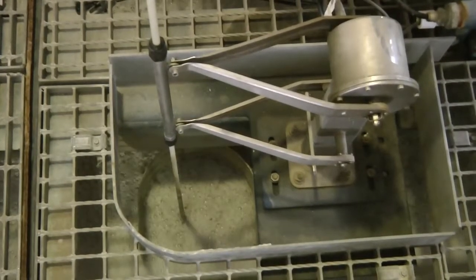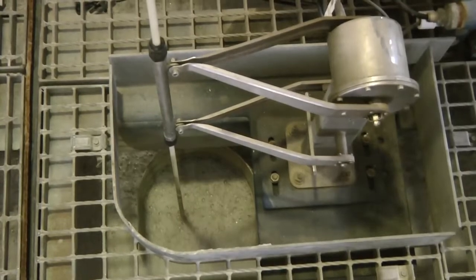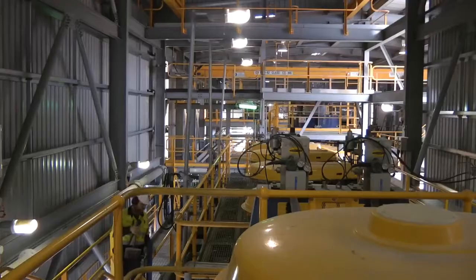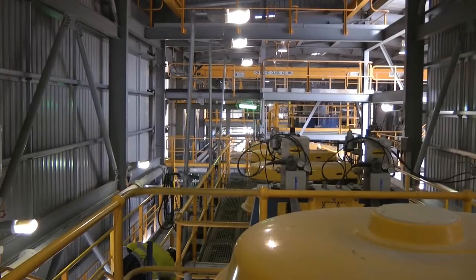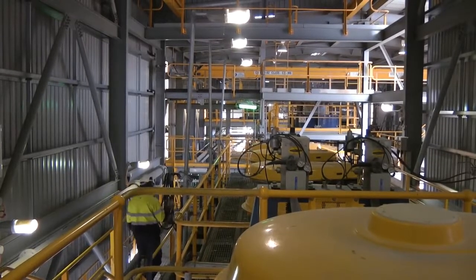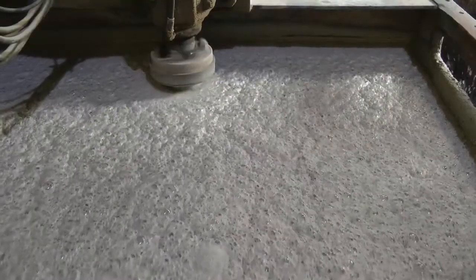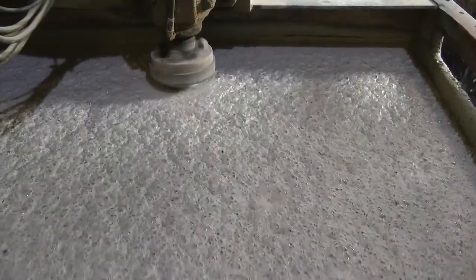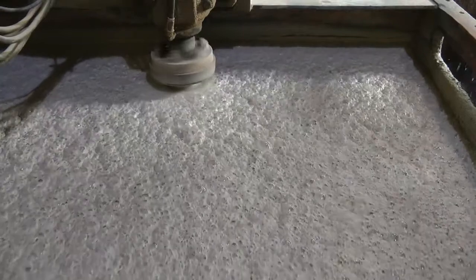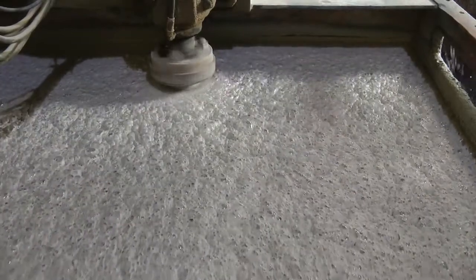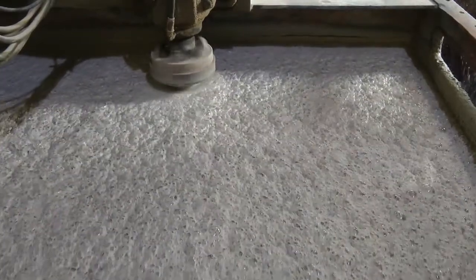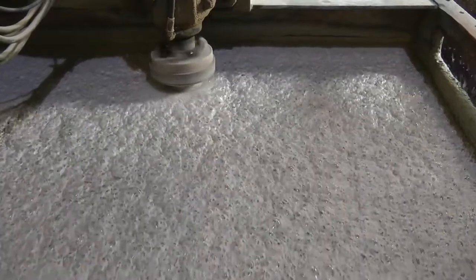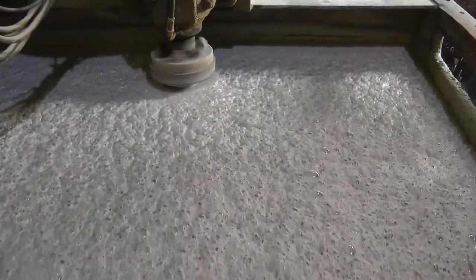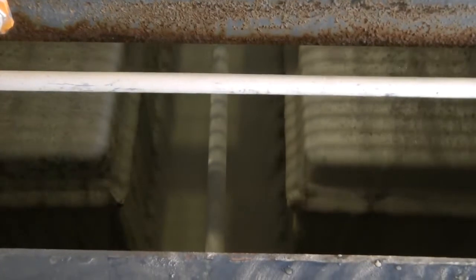Collectors, which are usually surfactants, for example oleic acid, are added to the pulp. They will make the lithium minerals hydrophobic by activating the surface. The pH is adjusted to be slightly basic, between 8 and 10 approximately. Foaming agents, typically alcohols, are added, which will decrease the surface tension of the pulp. This will prevent coalescence of the bubbles and thus make the foam compact and stable to make the process more